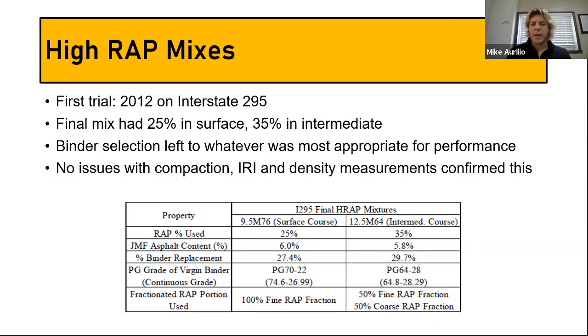They had no issues with the compaction. They measured the roughness, measured the density, and they were able to confirm this after their analysis. Basically, it compacted and paved as well as a virgin mix.